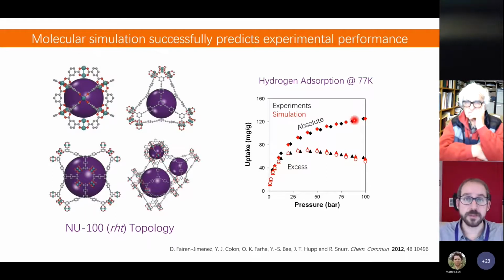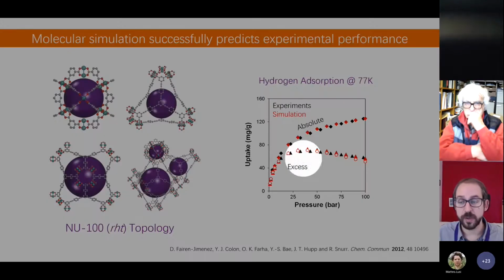In black is the experiment without looking at the simulations, and in red is the simulation, again, without looking to the experimental data. The simulation is not a match, it's not a fitting of the experimental data using Langmuir equation or anything like that. It's basically ignoring anything from the experiments apart from the structure of the material and just using statistical methods to be able to predict the performance of the structure. So really, really good agreement.